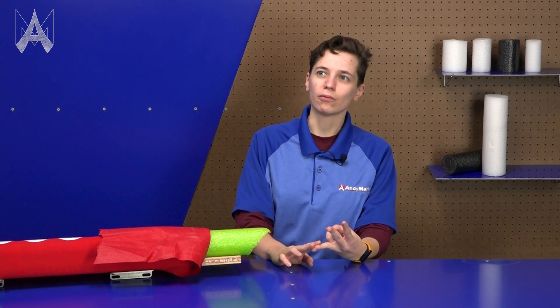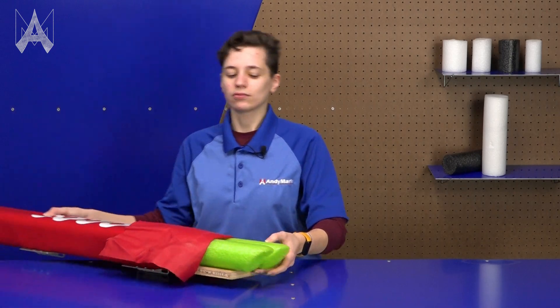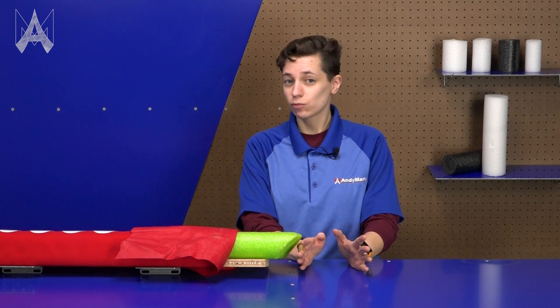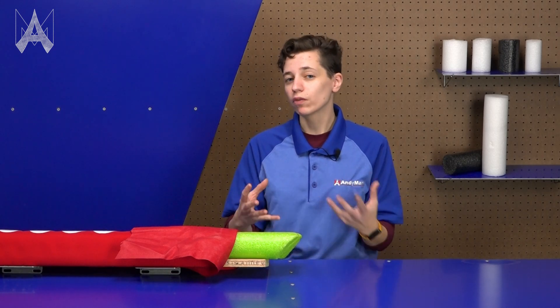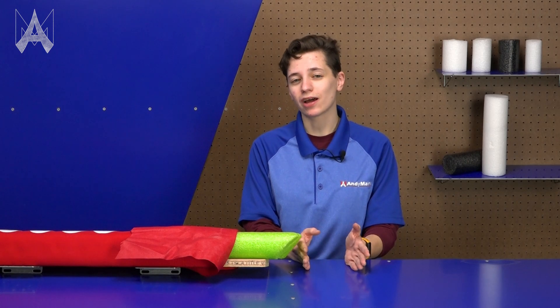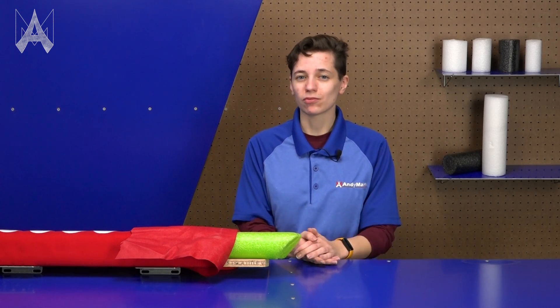In this testing, we tested plastics like HDPE, metals including 1/8-inch aluminum and 1/16-inch aluminum, and also wood as teams are familiar with in construction. This is currently the construction of a 2024 bumper — teams are required to use three-quarter-inch plywood and pool noodles on top. Through our testing, we found that newer materials like plastics and aluminums didn't do as good a job at dissipating force as wood. Plastic tended to bend as soon as it was hit by either a robot or a static field element, and aluminum, while it did well in some lower-load testing, unfortunately bent on the field and created damage to the robot's frame. Wood performed the best because of its ability to dissipate some force alongside the bumper foam in front of it.